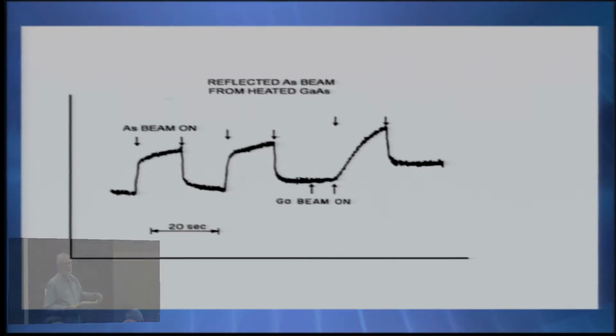The next slide, please. So I tried it with arsenic. Tried doing the same thing with arsenic. And in arsenic, the behavior was quite different. Now you can see that when I turn the beam on, there's an abrupt rise. There's no decay in the rise, and there's a gradual increase in the arsenic beam coming off just because the background arsenic pressure is getting higher. But then when I turn the beam off, it comes right back down.